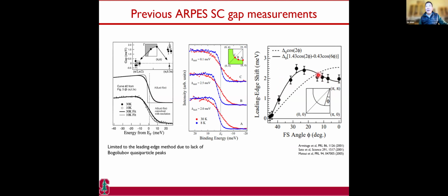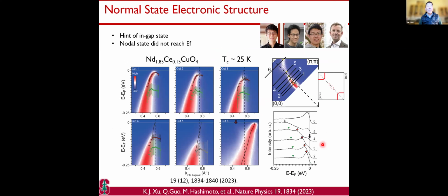This non-monotonic behavior of the gap was also seen early on. It was seen in particular in Sato and Matsui's paper, and it's consistent with the earlier work by Peter Armitage. So what we see here is consistent with the earlier work. However, in none of the earlier work were you able to see the superconducting coherence peak. So there's always a concern that this profile of the gap, which you'll see is consistent with the pseudogap, can be confused as being the residual of the pseudogap, because it's not clear you can prove this is superconductivity. Okay, and that's some of the recent data. As you can see, if I go cut around 1, 2, 3, 4, 5.